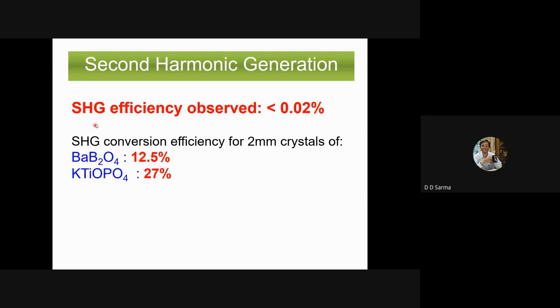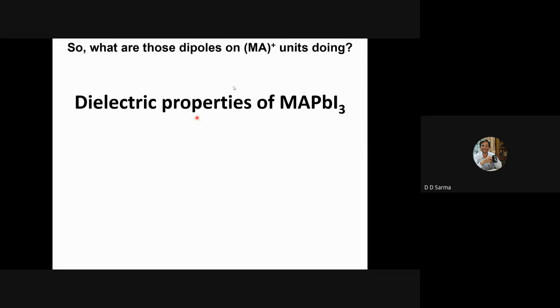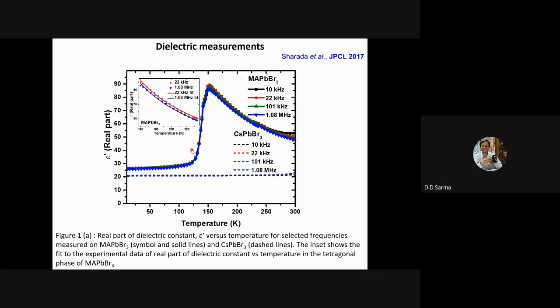I'll only tell you the result, that we find the second harmonic generation efficiency is below the detection limit, and our detection limit is 0.02%. Whereas a polar material would have several tens of percent efficiency. Again, showing it's not a ferroelectric material. And what are the dipoles doing? They must be disordered. They can be dynamically disordered or